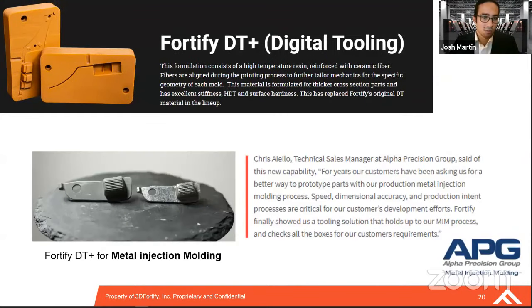And one more tooling example. We've done a lot of work with metal injection molding, and this process is one where you're shooting very densely filled compounds into a mold. This is stainless steel. You essentially have a 55% by volume metal powder within a resin that's injected into these tools. And so it's very abrasive, high temperature or high pressures.